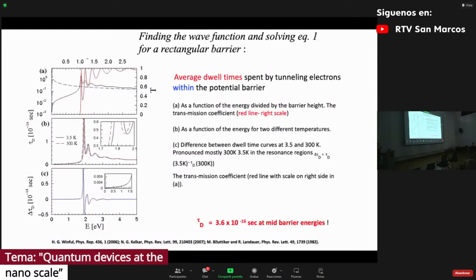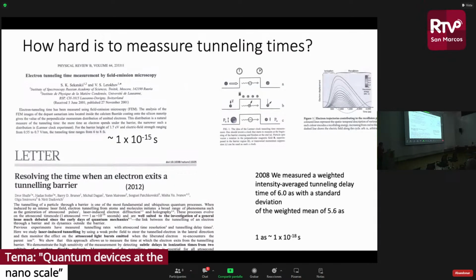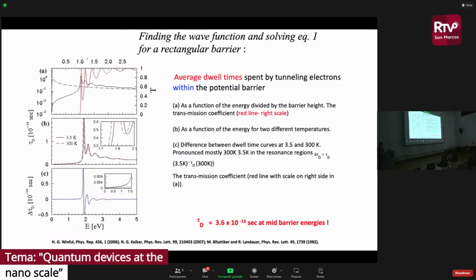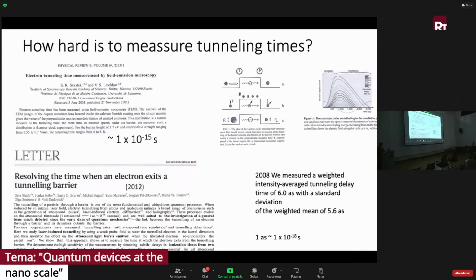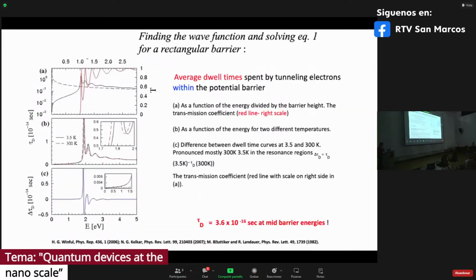So we do it through extrapolation with the theory. We take the theory, we take our data, and we extrapolate, and we get 3.6 times 10 to the minus 16 seconds at mid-barrier energies. Contrary to what people know, that was the first time we extrapolated tunneling time from actual solid-state tunnel junctions, because these other tunneling times are not from junctions; they are other systems which do quantum tunneling, but not tunnel junctions. We are quite happy because it's near the order of what people get, but this is a more exact measurement, because the other ones are just approximate, since it's impossible to have a direct measurement of tunneling time.